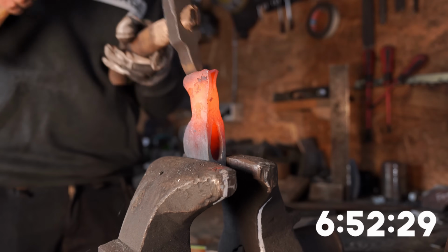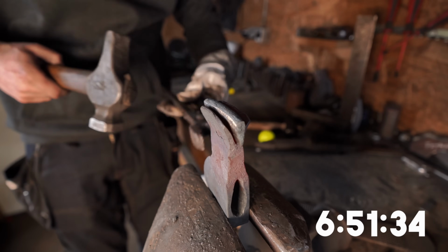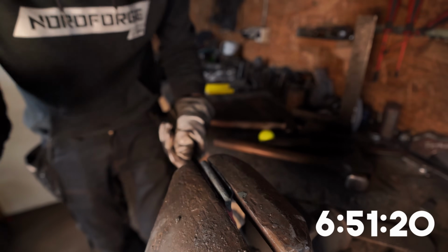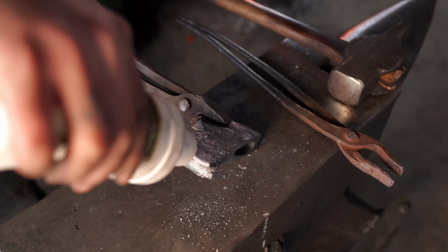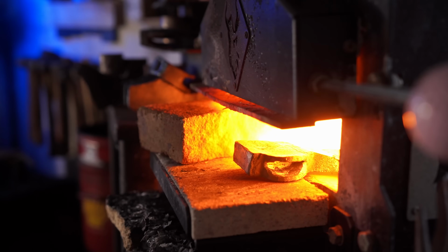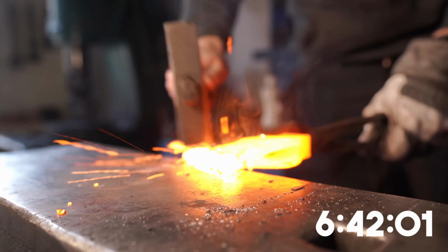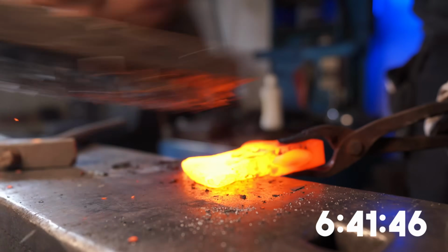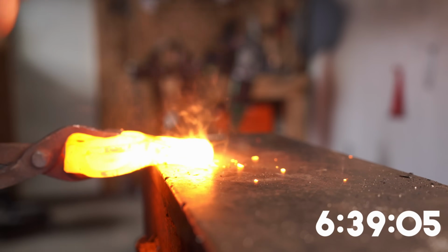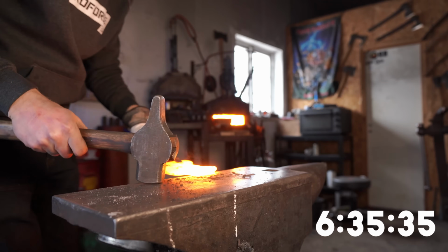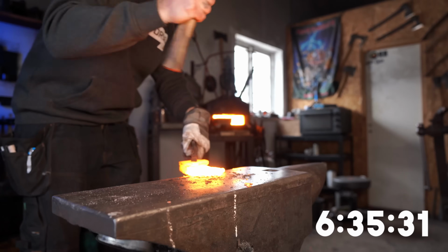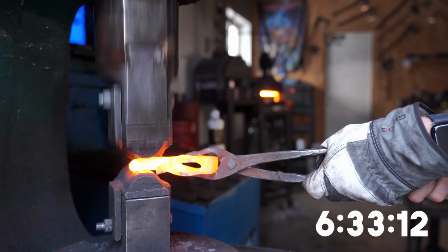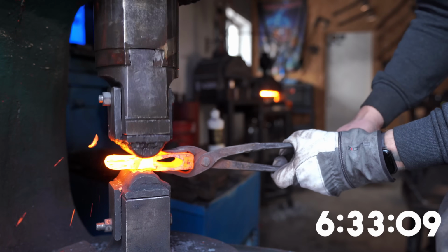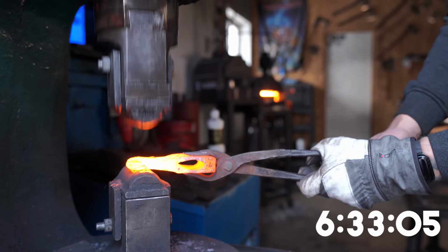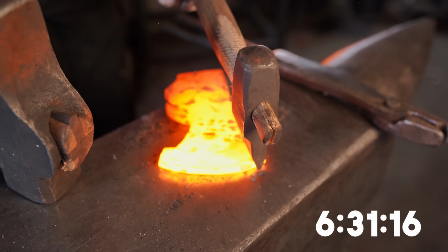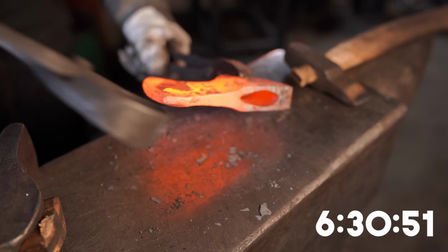I then split open the slot once more and insert the edge steel. I then press the slot shut using the jaws of the vise. After that I flux it, bring it up to forge welding temperature, and then it's time for forge welding. To remove the excess material, I use a hot chisel and cut it off. I then clean up the cuts with some hot rasping.